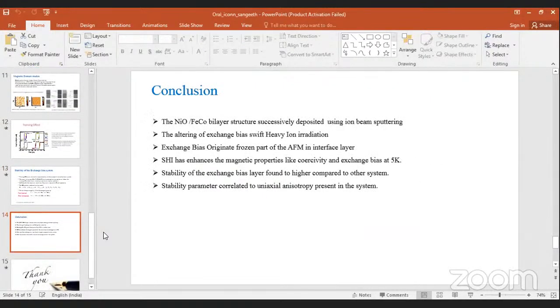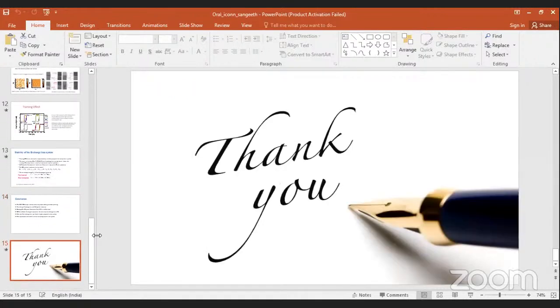So in conclusion, we have deposited the NiO/FeCo system, and it shows exchange bias at lower temperature. The irradiation has enhanced the coercivity and exchange bias at lower temperature. The stability of the exchange bias was found to be higher compared to the other system, and the stability parameters are correlated to the uniaxial anisotropy present in the system. Thank you.